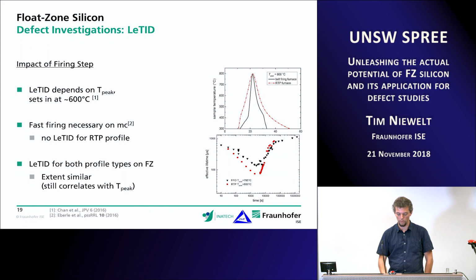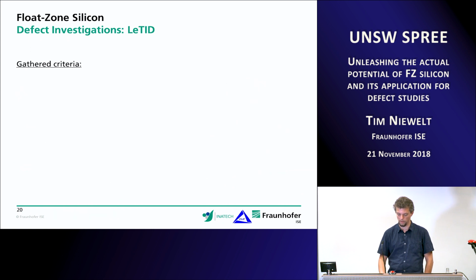However, we've seen in float zone silicon quite recently that samples that underwent very similar temperature profiles do degrade, both of them do degrade. We have a slight mismatch with the peak temperature, but the trend is aligning fine with what we've seen for multicrystalline silicon. So for float zone silicon, we see that the degradation also occurs with the slow firing, which could be quite interesting for the model of the defect.